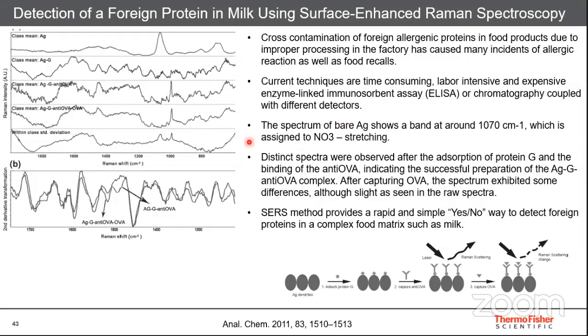Raman, on the other hand, as I said, doesn't need sample preparation. So here is what they have done. They have taken the silver dendrites, and the particular protein which they want to see has been put on these silver dendrites. This is OVA, that is ovalbumin, which is what they wanted to see. They captured it with anti-OVA, then took the spectra of that compound, and finally captured the targeted material and saw the effect.